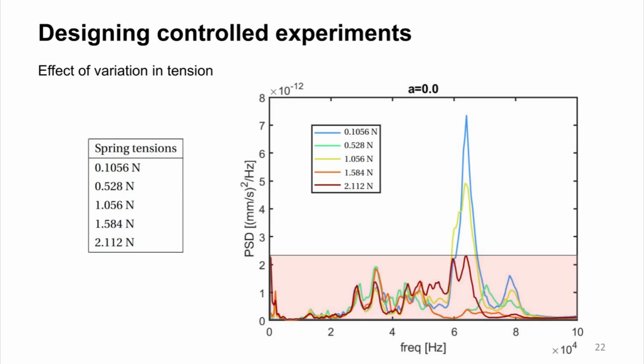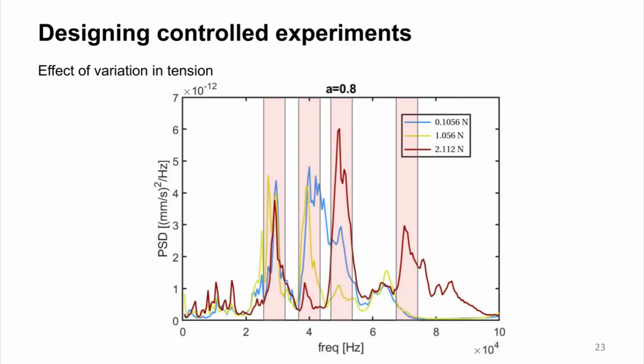And some of the intermediate tensions for which the Bragg peak completely vanishes is below 2 N. Also found that perturbation strength of 0.8 has a tension dependence, and it has a very non-linear, non-monotonic tension dependence as the previous one as well, and the dependence varies across different peak features for this metamaterial.